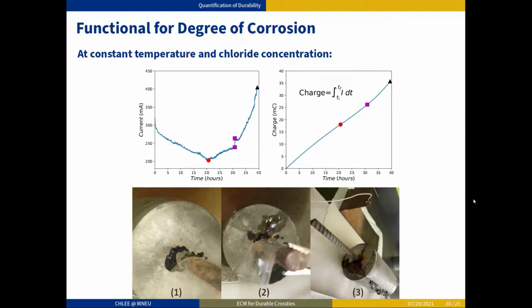For durability performance of developing ECM, we found out that the charge, which is the integration of current measurement, is a pretty good indicator for tracing the degree of corrosion. If you see the bottom photos, there are three different states. Number one, there is no visible crack. However, we found out the corroded products were leaking from the top. Then at stage 2, you can see slight visible cracks on the surface of the specimen. However, in this stage, you cannot find the longitudinal crack as shown in picture 3. So, states number 1, 2, 3 are indicated on the graph by the red circle dots, the magenta square dots, and the black triangles over here.